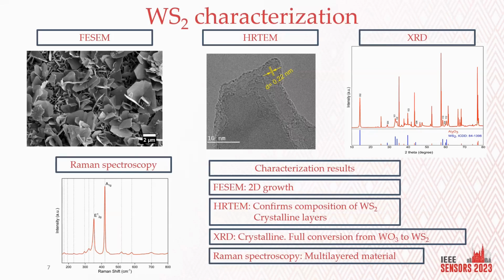Moving ahead towards XRD, X-ray diffraction, it confirms the full conversion of tungsten trioxide to tungsten disulfide and confirms the material is highly crystalline. Moving ahead towards Raman spectroscopy, the results confirm that our material is a layered material, a multi-layered material actually.